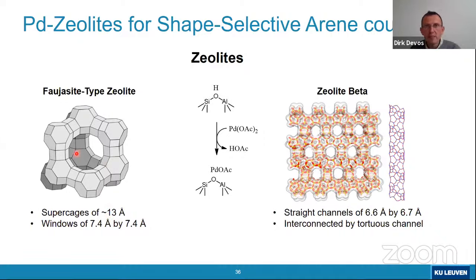Of course, you can go to very small porous zeolites like you would have in the Denox catalysts, but that's of course useless because then even the reactants like toluene or xylene could no longer enter the pores. But zeolite beta could strike an interesting compromise because the pore sizes are still large enough to allow the diffusion in and out of the reactants and even products like bitolyl, but still the pores are quite more constrained than what you would have with a faujasite zeolite.